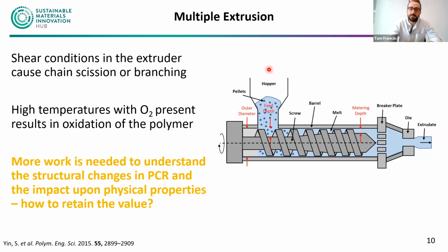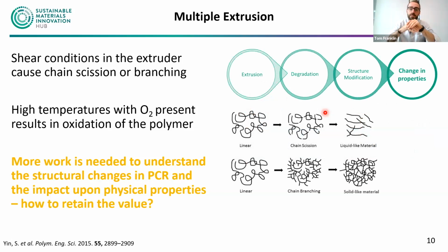You take your solid polymer, in this case pellet feedstock, and you feed it into a barrel with a rotating screw. And when you apply heat and you apply shear, you melt those polymers, you mix them together, and you can then push them out of the other end through the die into a filament, which we can then characterize. And the key thing about this form of recycling, which is termed mechanical recycling, is that it can be quite a harsh process on your polymer. So we've got high temperature, we've got high shear, and we've got oxygen present within this system. And all of that leads to degradation of our polymer chains.